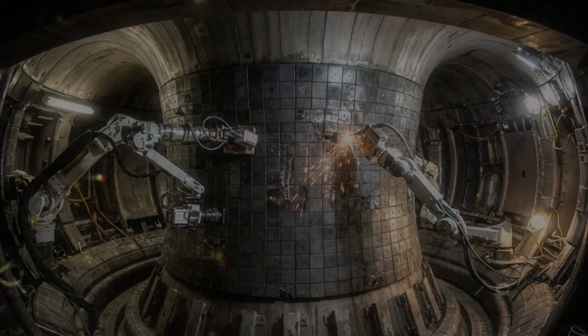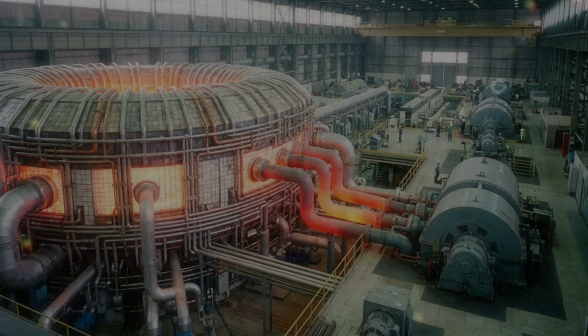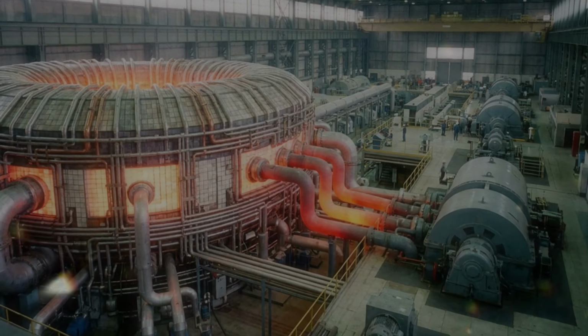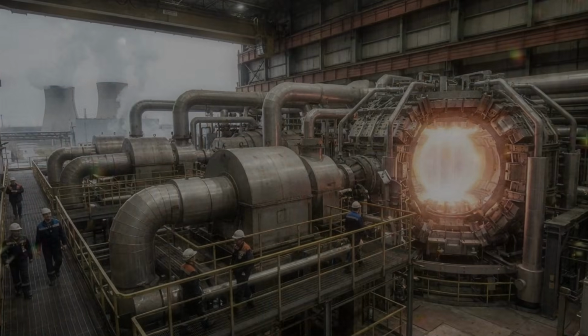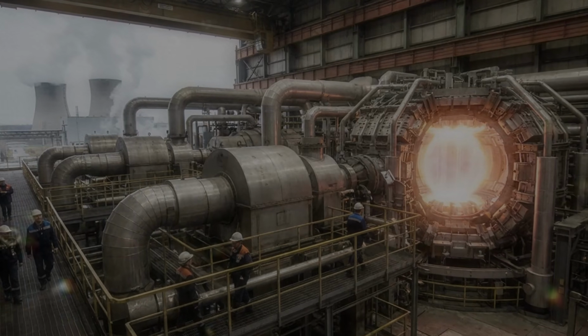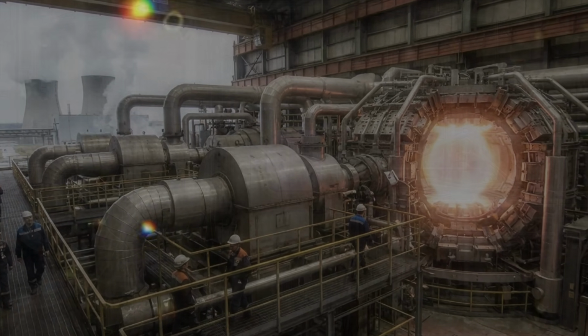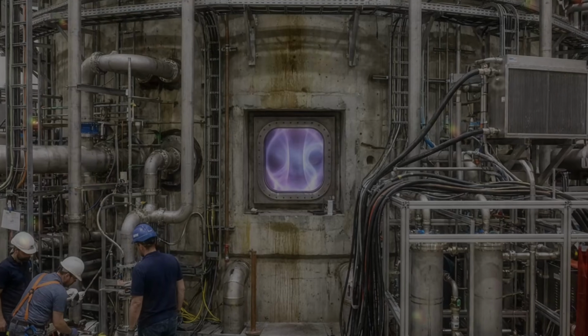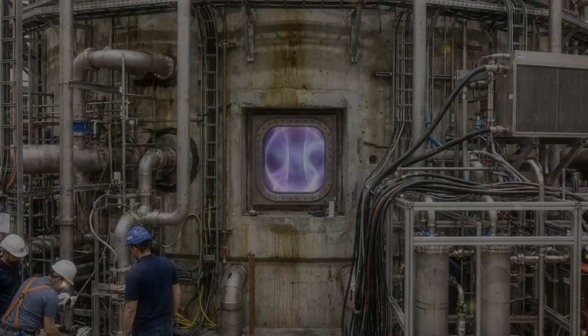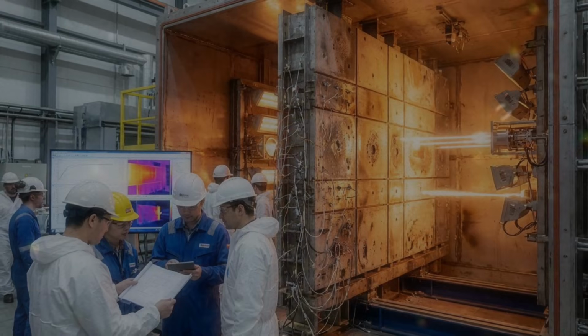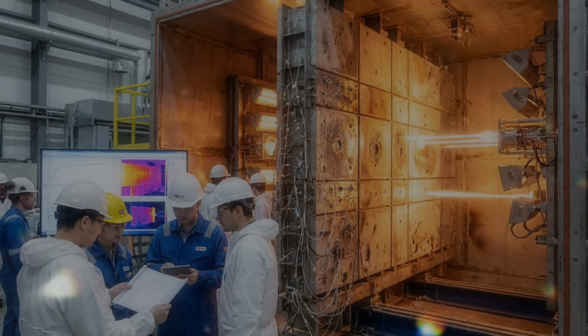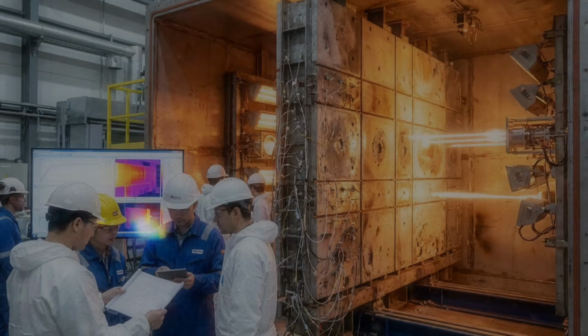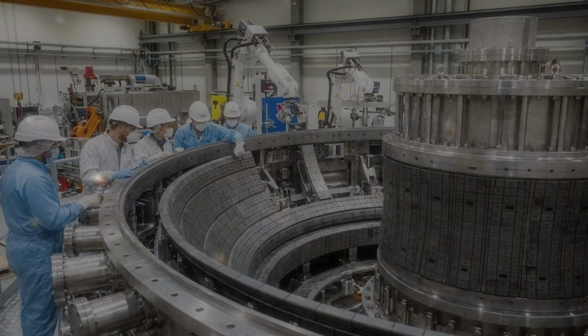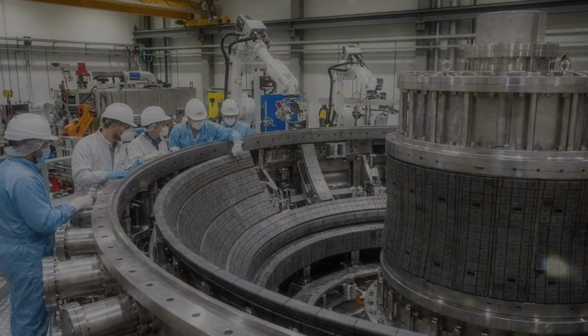In experiments, lithium coatings and lithium-conditioned walls have sometimes improved plasma performance. The plasma can become cleaner, edge behavior can change, and confinement can improve. It is as if the wall, instead of bouncing particles back into the plasma like an impatient tennis partner, begins absorbing some of them and calming the edge. A calmer edge can help the core remain hot. The core, in turn, is where fusion wants to happen, so a surface only a few atoms deep can influence the behavior of the entire plasma. Once again, the boundary becomes part of the star.